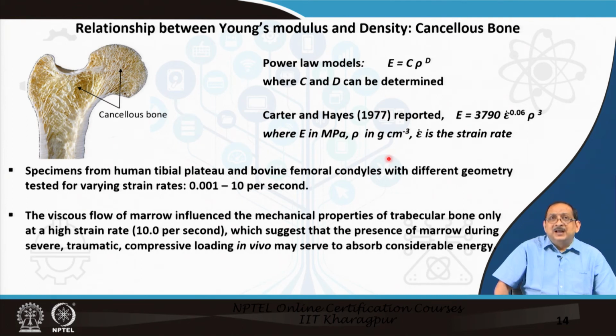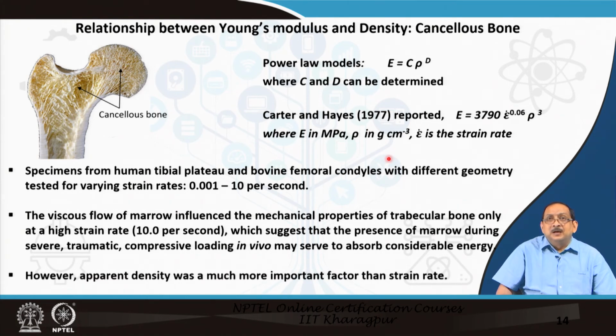It was observed that the viscous flow of marrow influenced the mechanical property of trabecular bone only at high strain rate, which suggests that the presence of marrow during severe traumatic compressive loading, say for instance an impact load, an accident case, in vivo may serve to absorb considerable energy. But overall, it was concluded by Carter and Hayes that apparent density was a much more important factor than the strain rate to define the relationship between Young's modulus and apparent density.